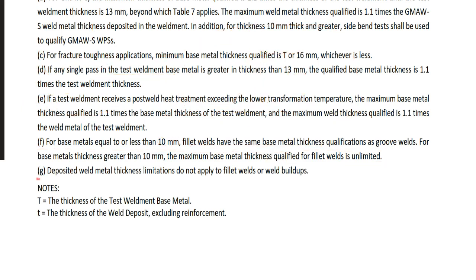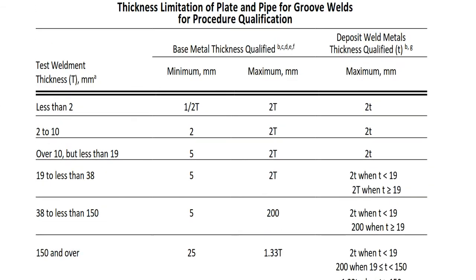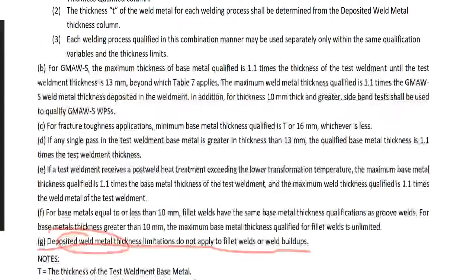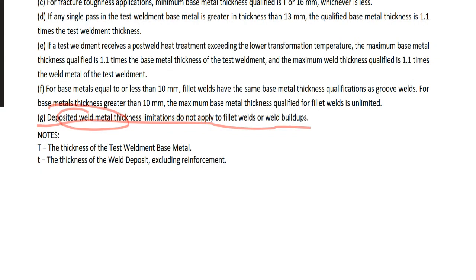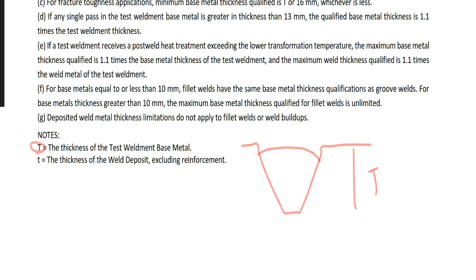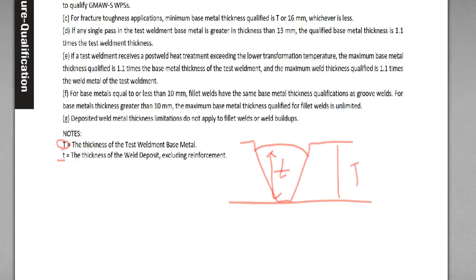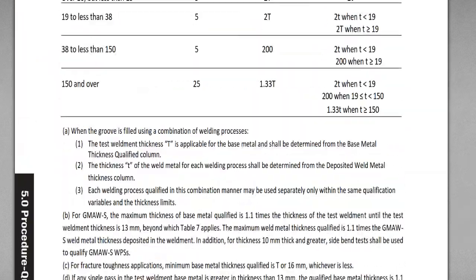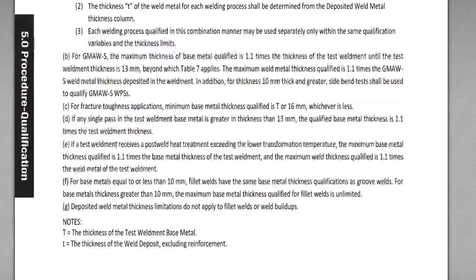G, deposit weld metal thickness limitation does not apply to fillet weld buildup. So deposit weld metal thickness is not applied to fillet weld or weld buildup. Weld buildup is something like buttering or overlay. And this large T is the base metal thickness, and small t, lowercase t, is this weld metal thickness. Okay, this was table 7, and notes A through G.